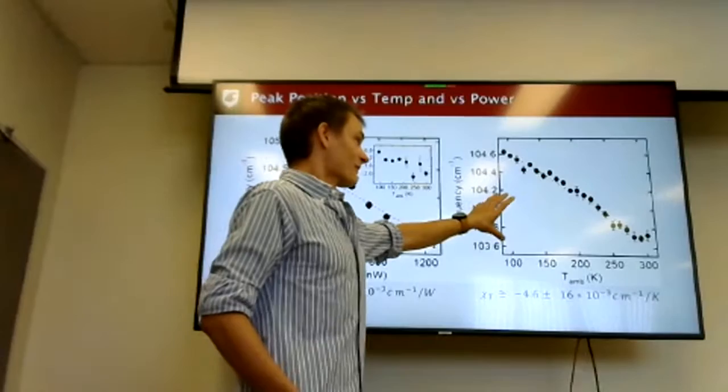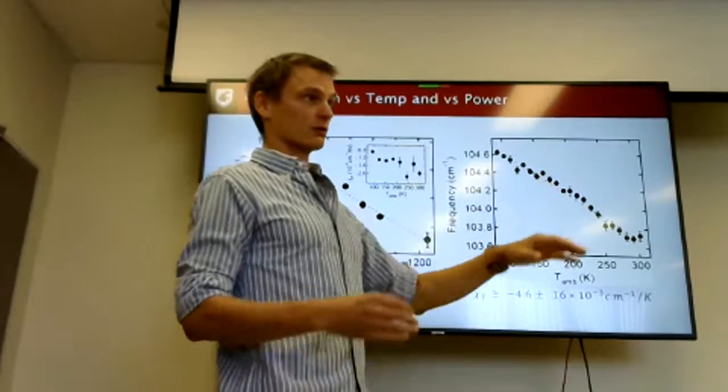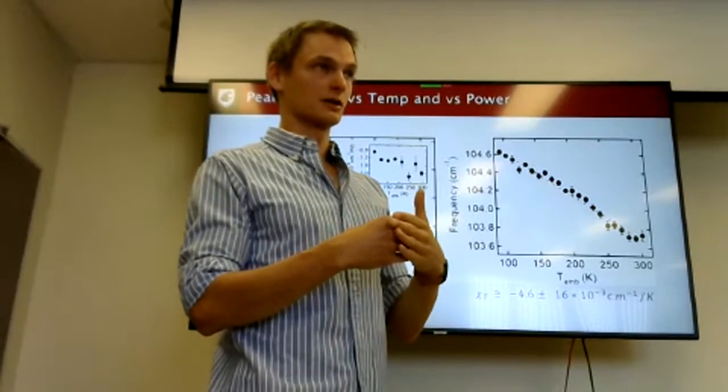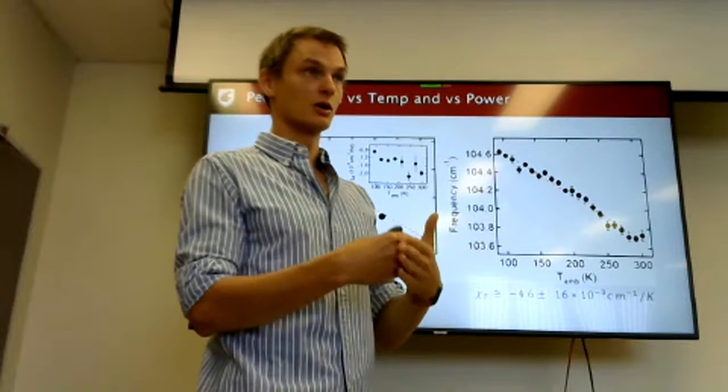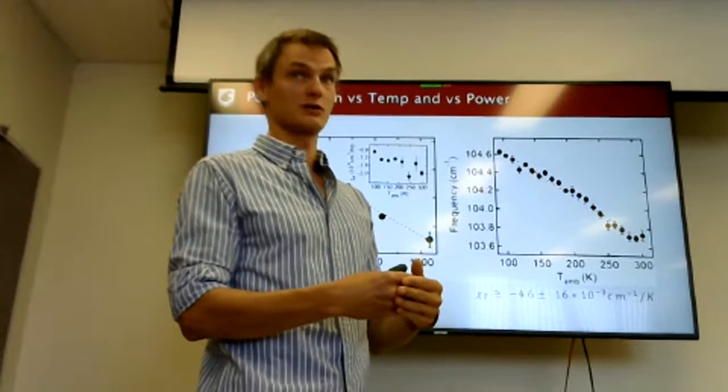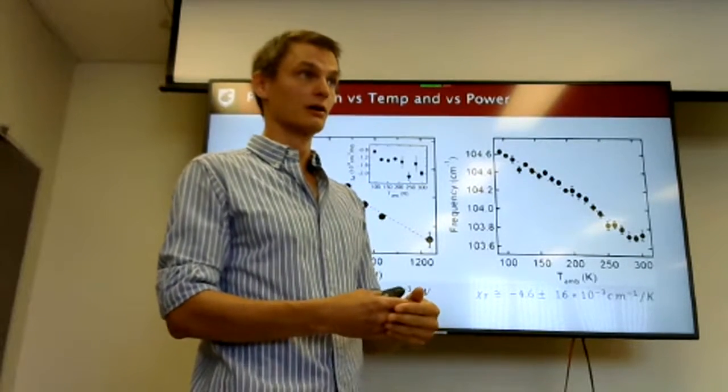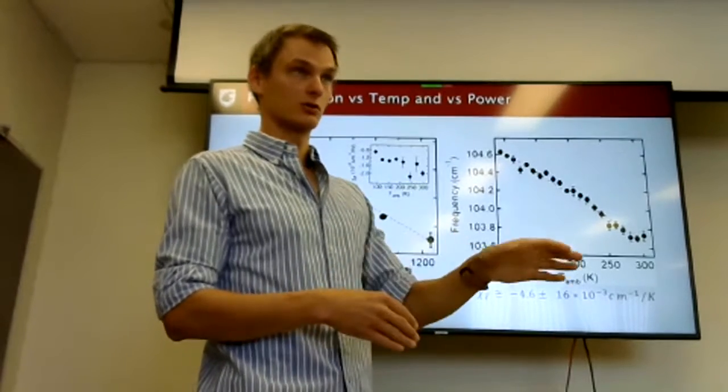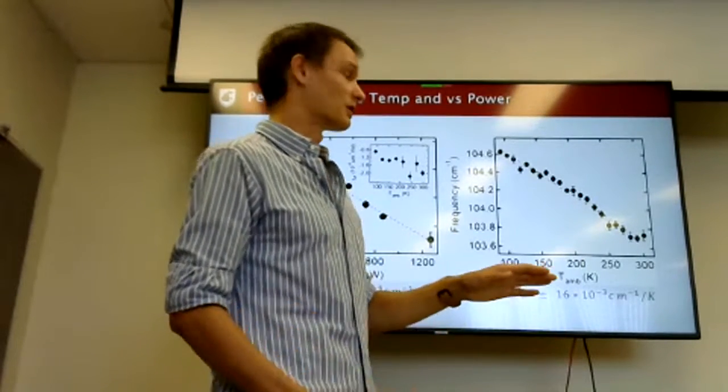So for this one, we did a slightly different experiment where we put the indium selenide on the substrate without a hole because we wanted there to be no heating. And then we used a very low laser power and a very long integration time to keep it from heating. And we made sure that there was no laser heating going on in this experiment.